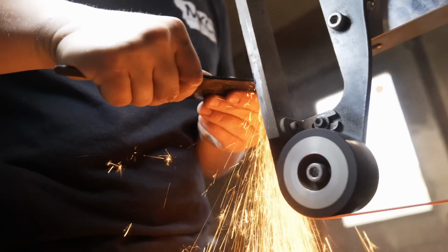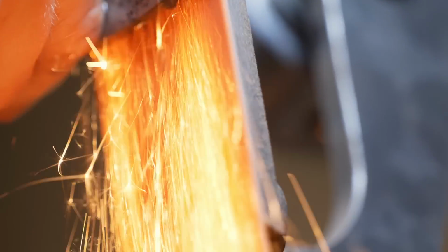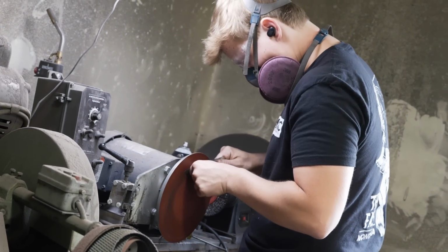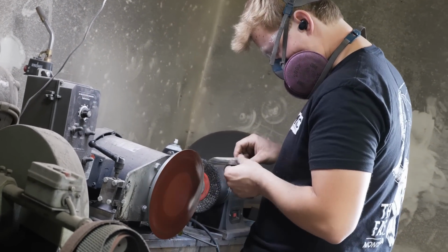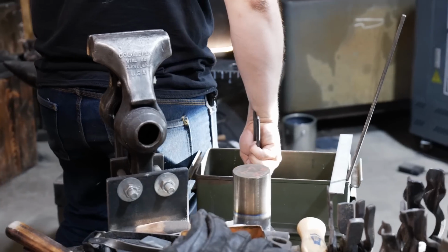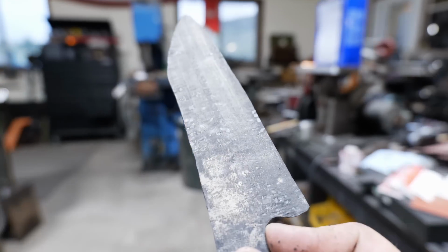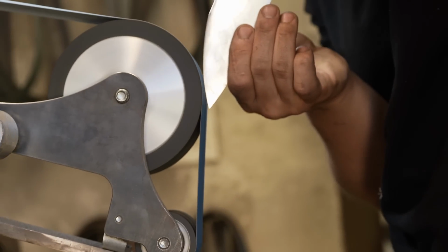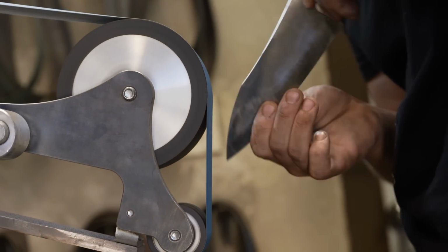And so you can't get a part or a knife to the finished state and then harden it, because you're going to mess up the surface finish of almost anything when you bring it up to 1500 degrees and then quench it in oil or salts. There are a couple ways that you can get around it, but for the most part, you have to refinish or even remove a decent little bit of material after you've done your hardening process. That adds a layer of complexity and a layer of challenge into doing mass production pieces out of Damascus. It's just not super easy.